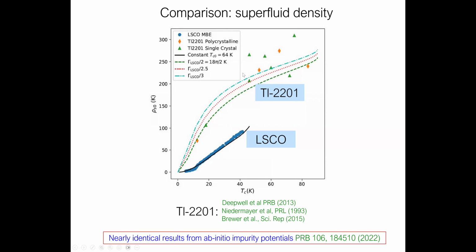We need to take the scattering rate due to dopant atoms in the thallium system to be about a factor of 3 smaller, factor of 3 cleaner. And that accounts for not only the superfluid density, which I've shown here, but also the optical properties of LSCO, the thermal conductivity and specific heat of thallium, which I don't really have time to show you right now.